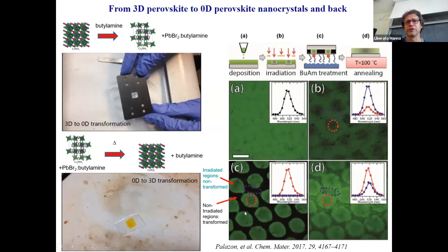And the non-irradiated region converts into the 0D phase. You can heat the film and go back, almost entirely, to the original PL emission, also from the non-exposed phase. So you see, this is an interesting effect of chemical transformations on these perovskite nanocrystals, which are materials that are very much prone to different sets of chemical reactions.